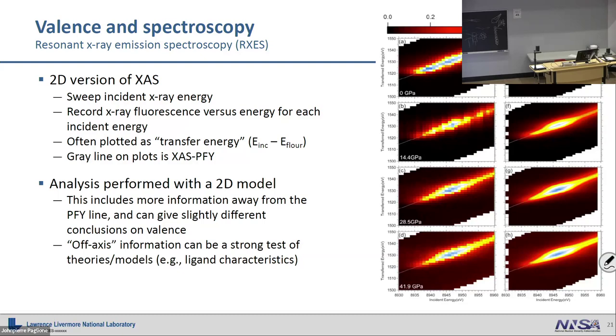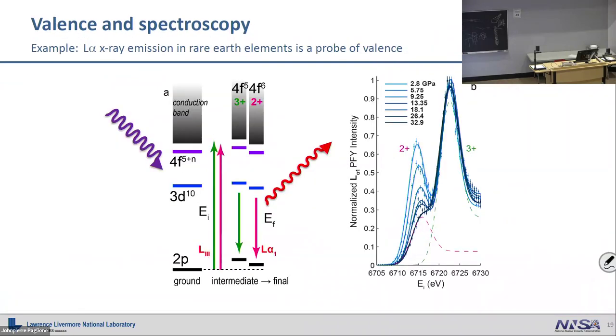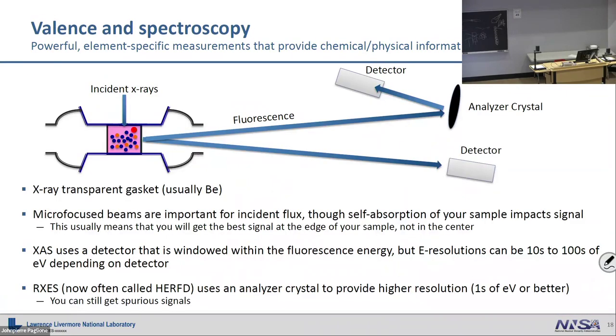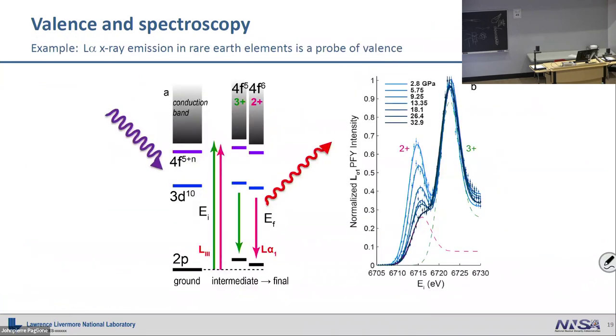It's a little more complicated. If you're a DAC person, it's no more difficult to make one DAC versus the other. It's just a matter of whether the beam line is set up for that kind of measurement. More and more beam lines are being set up with this kind of high energy resolution because they're there. And if you don't want the high energy resolution, if you want this setup to look like this one, you just fix the analyzer crystal somewhere and it goes right back to the old one. So more and more they're setting up in this way, so you'll have access to that as you go forward.